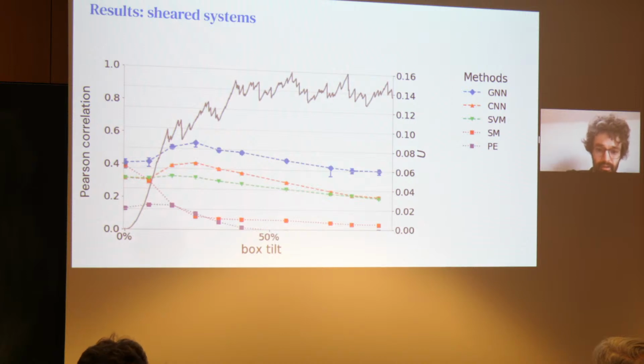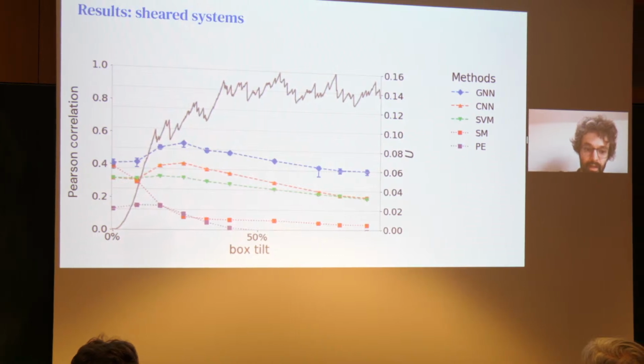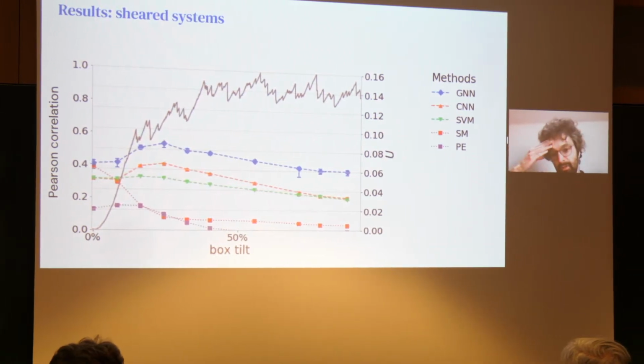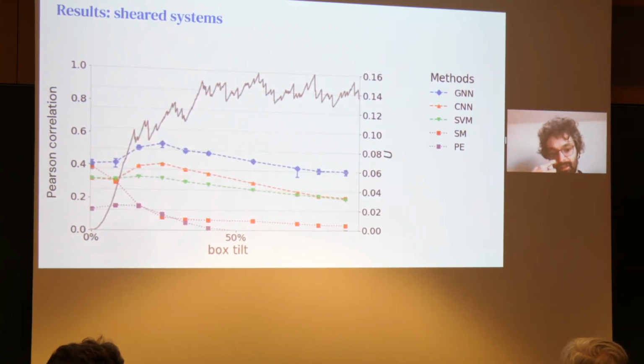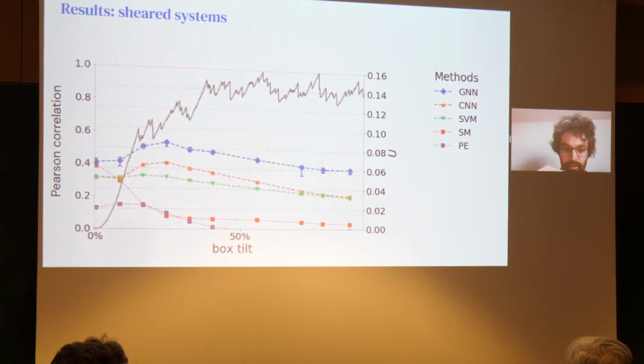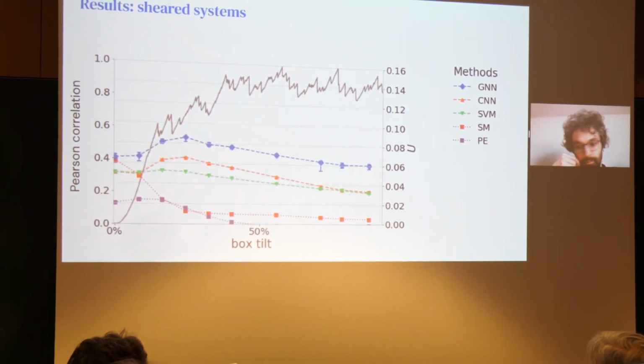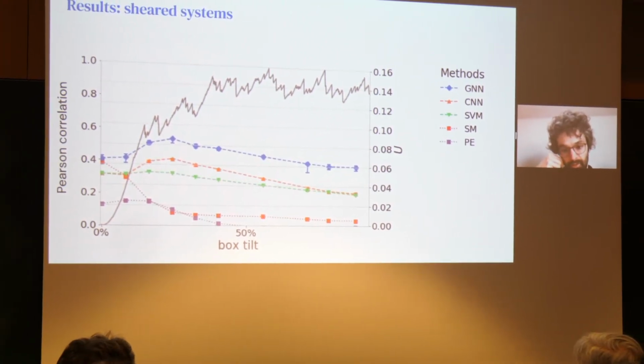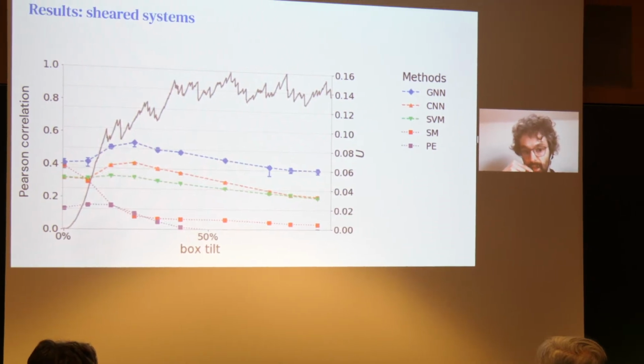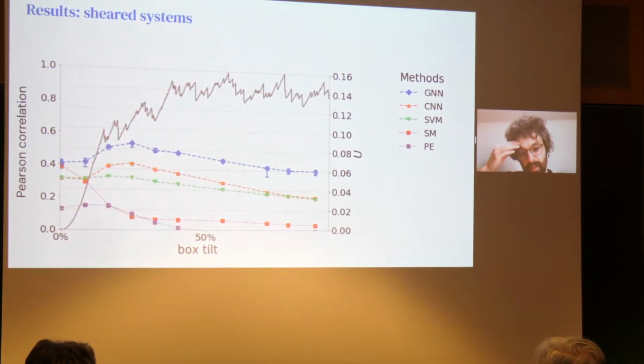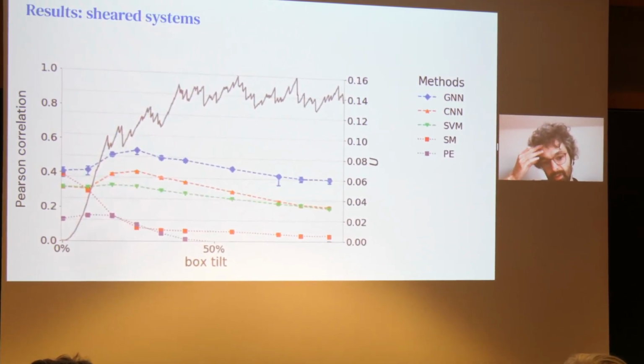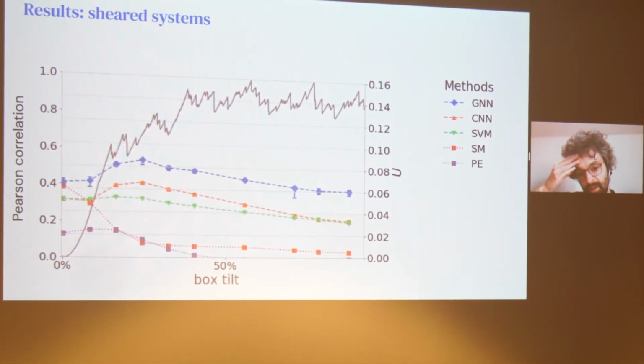These were results on thermal systems. So now we looked at the non-thermal systems, doing plastic deformations on the system, and again comparing the model to either other machine learning approaches or physics-based approaches, and again seeing a good correlation as you increase the strain and especially at intermediate shear deformations.